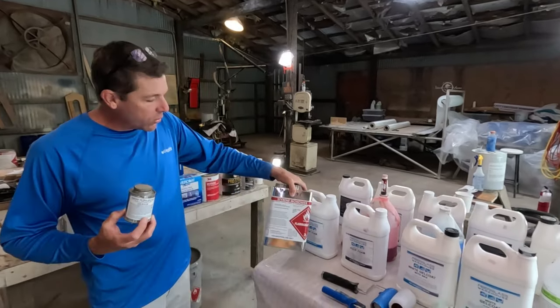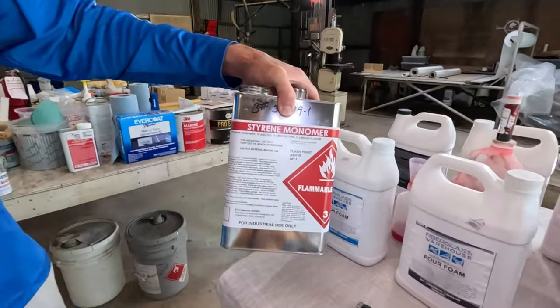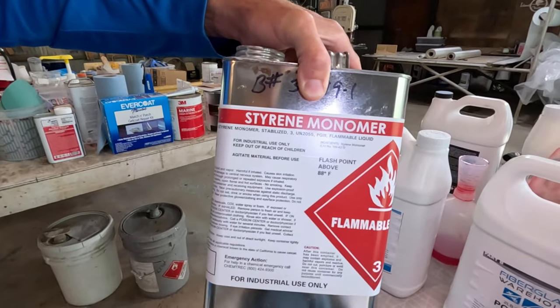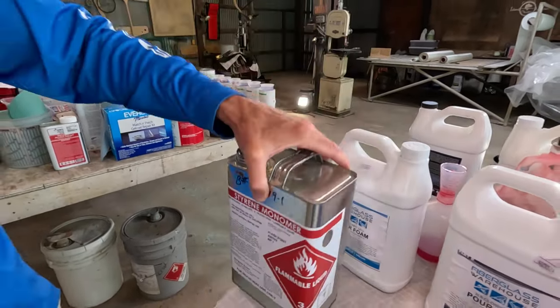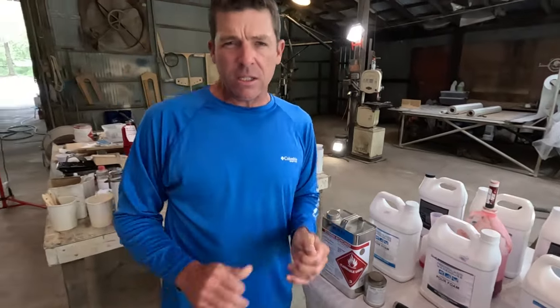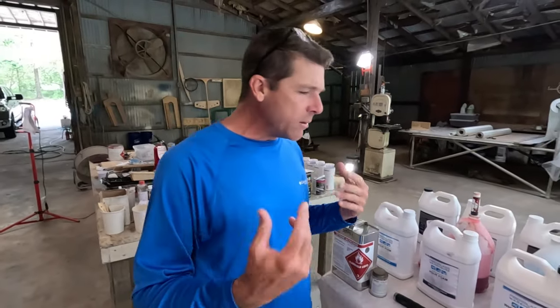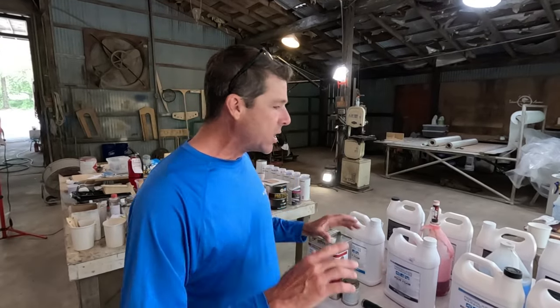We also, if you're wanting to thin your gel coat, this is gonna be the solution. Styrene monomer. No more than about 5% typically by volume. Any more than that and you can affect the color outcome of the gel coat. I don't recommend ever using acetone, guys. Sometimes people say acetone for thinning gel coat, but styrene is the correct.